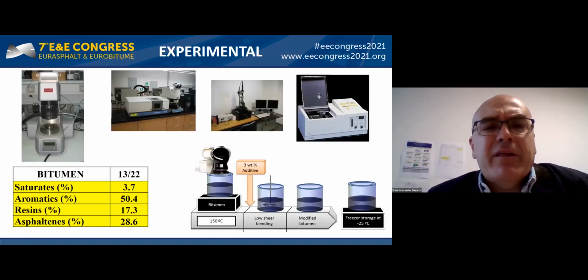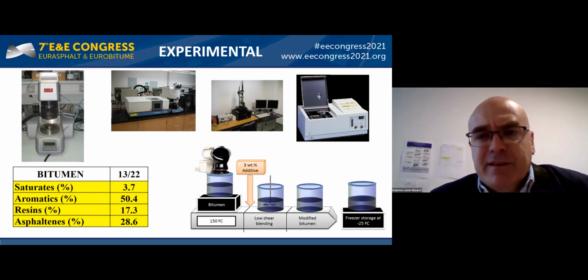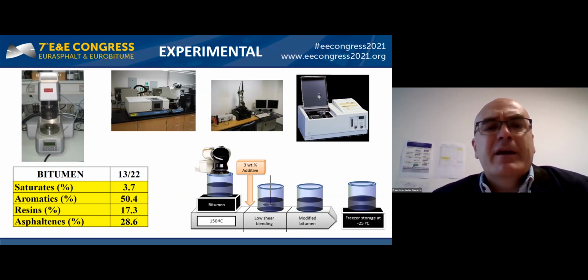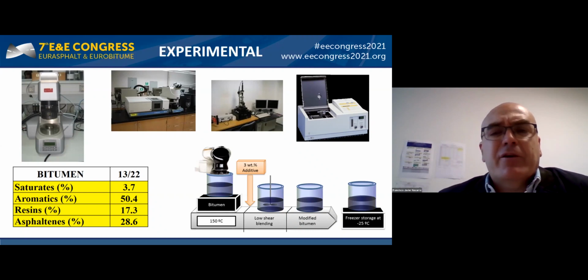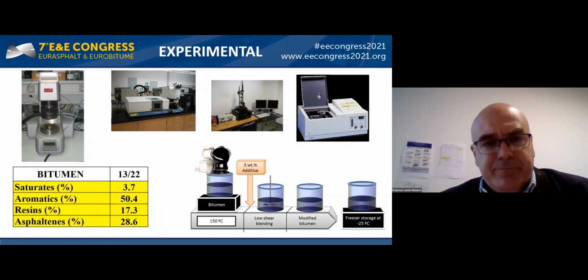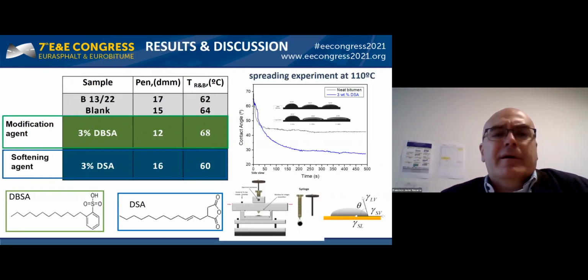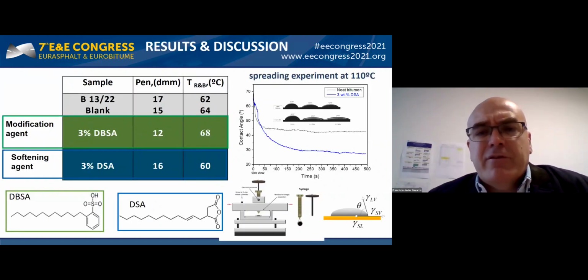In general, a hard 13/22 bitumen was employed as a base material for this study and modified with 3% of every reactive surfactant. After modification, samples were submitted to rheological characterization, infrared spectroscopy, thin layer chromatography, atomic force microscopy, technological tests, etc. First of all, a preliminary study based on conventional tests has been carried out in order to analyze the potential modification of the selected additives.